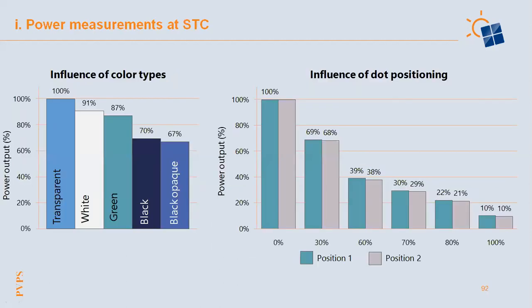From the results, you can see that in terms of power output, we have a range of reduction in comparison to a transparent model that runs from 9% to 33% for the worst case, so the black opaque model. But for instance, the white model and the green still have good performances and good power. We can say that the dot positioning in this case doesn't affect the power output, as you can see here from the graph on the right.